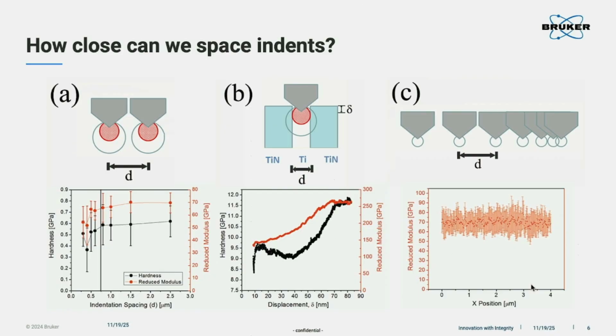Secondly, if you have a multi-phase material, then you can see the boundary will also affect our data. That we call the size effect, right? So we want to make sure the elastic zone will not exceed the boundary. So how do we control the elastic zone? Of course, we need to control the depth here, right? For example, this elastic zone is too big because this is over the boundary. The data you get, the modulus, is not what we want, right?